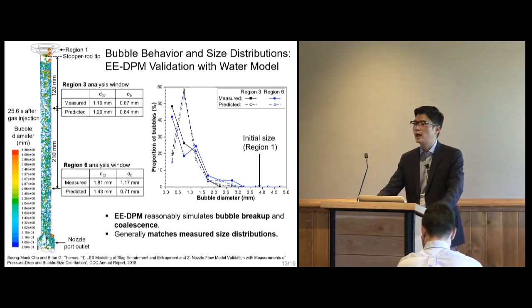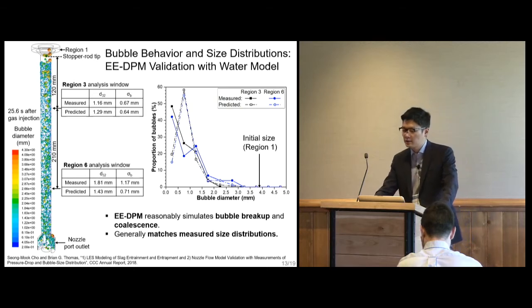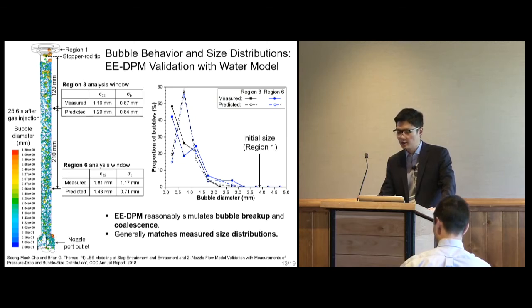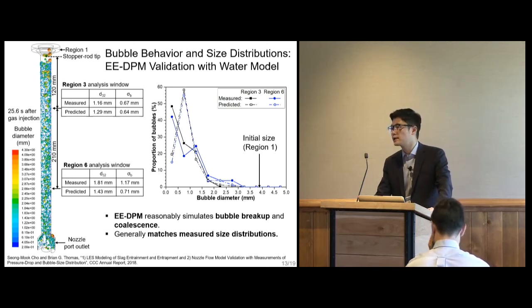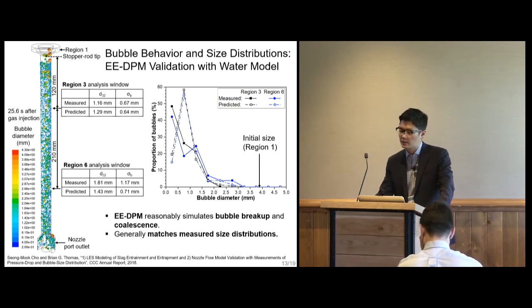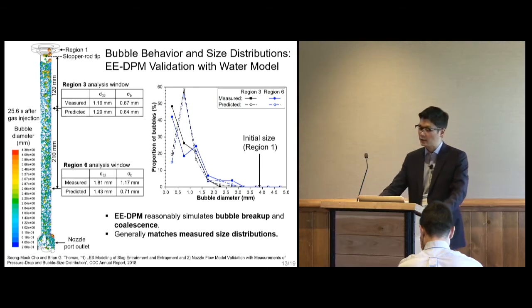We used the new hybrid multiphase model, EEDPM, to simulate the bubble behavior, including the bubble pocket formation, shearing off, volumetric expansion, and the breakup, accumulation, and coalescence. The model can calculate the bubble size distribution change more accurately, considering all these phenomena. The model was validated with the water model experiments.